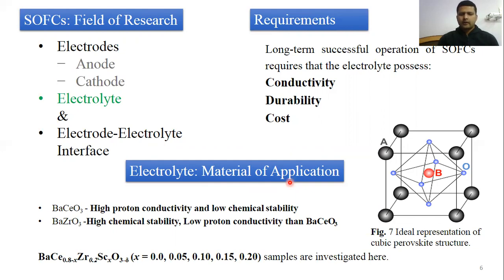Of the many known perovskite materials, those based on barium cerate exhibit a high proton conductivity, while barium zirconate possesses high chemical stability. So a suitable concentration of zirconium is added to barium cerate to compensate the trade-off between the two. The equivalent co-doping of scandium is investigated and discussed here. The figure shows an ideal representation of perovskite structure where A site is at the corner of the lattice, while B cations are at the body center of the lattice, and oxygen at the face center.